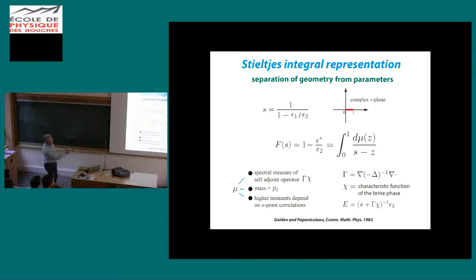Here's again just repeating this, and one of the key aspects here, this is what makes the method so powerful, is that all the parameter information is in that complex variable, and all the geometry of the composite is in the spectral measure. And this spectral measure is associated with a self-adjoint operator, gamma chi, or chi gamma chi, depending on how we formulate it. Gamma is projection onto curl-free fields: gradient, inverse Laplacian, divergence, and that's non-random. All the randomness comes in through the chi, the characteristic function of the brine phase, 1 in the brine, 0 in the ice, or 1 in the melt ponds, 0 in the snow, and so on, for a two-phase material.